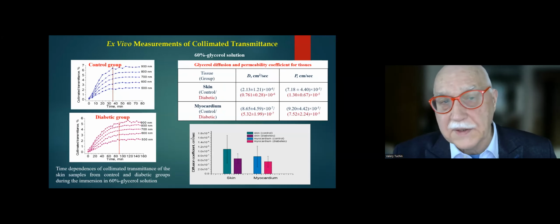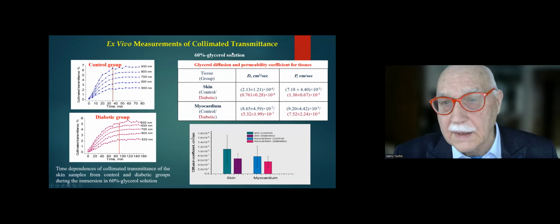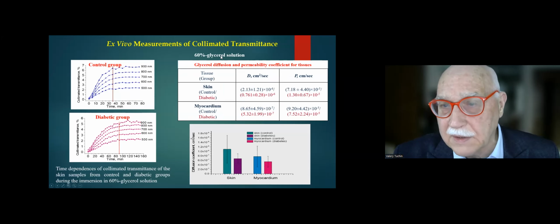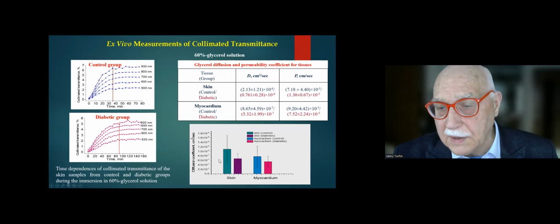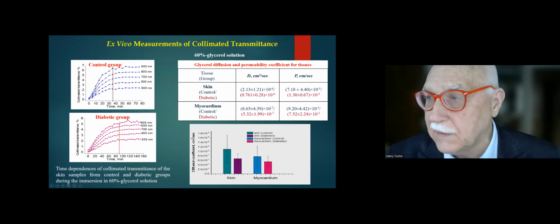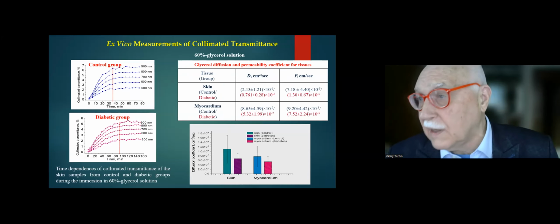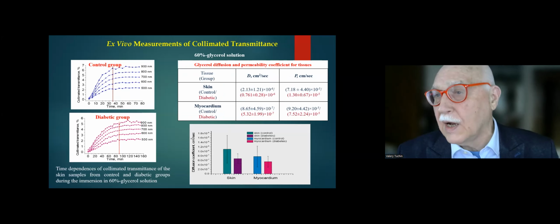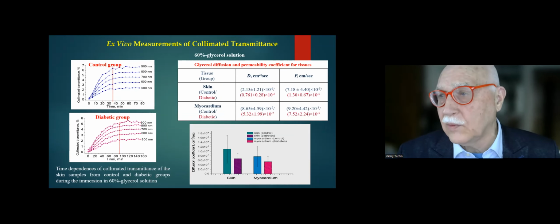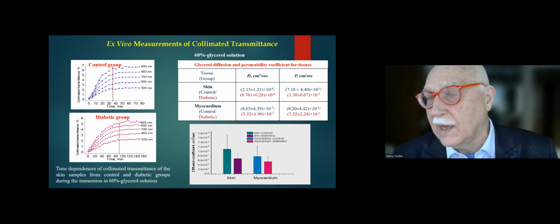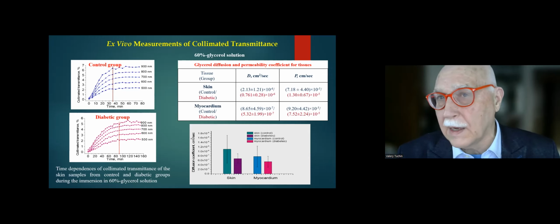So once again, these are numbers for another probing agent, like glycerol solution. We see here quite a good difference for skin and a correlation for myocardium. And these are the real numbers of the diffusion coefficient, which can be used for drug delivery, for example, for calculation of how much agent you have to give with the same molecular weight, shape and so on.